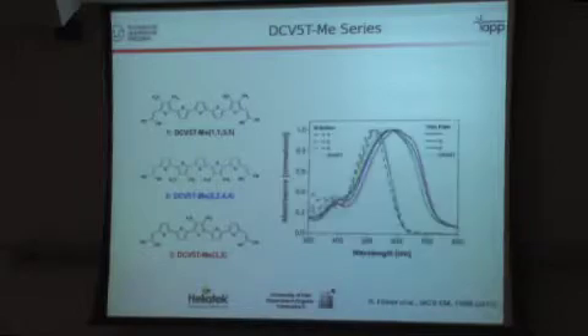But now let me come back to the question of crystal structure and morphology. We studied that in more detail in a paper which we published already 1.5 years ago. We took 5-ring thiophenes, which have the optimum voltage, and we took the methyl side groups. In this case, we used all methyl, but at different locations of the molecule. So a structure called 1, 2, and 3. And when you look at the solution spectra, they look fairly similar. There's a small difference for the materials.